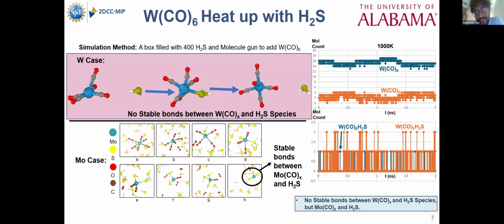But one thing to notice is that this is actually not a bar chart. This is actually a line curve. That means after every picosecond or every couple of picoseconds, you see that the species count goes down to 0. That means that the species are not stable, the bondings are not stable. I searched for species and found the reaction path, and we can see that one tungsten hexacarbonyl gets attached with one H2S, and after a couple of picoseconds, it gets detached again. So the molecules get separated again.